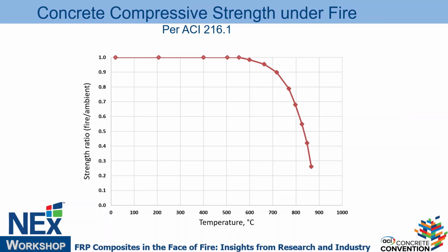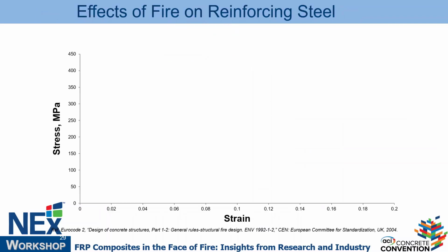So that doesn't mean when I have that temperature that all the cross-section of the element is falling apart, right? It depends on the temperature. So if, let's say, the outer 1 inch or 25 millimeters of the concrete reaches, let's say, 500 degrees, that means only the outer 1 inch is not contributing to strength, right? Not the entire section. And that keeps going with time. So the profile of the temperature through the cross-section is important to understand, because that gives me an idea of what's the remaining residual section that has adequate resistance during fire and which section is falling apart.